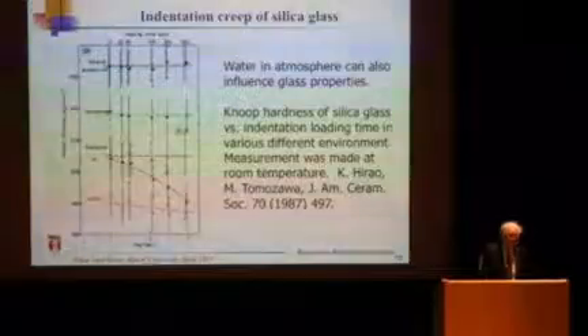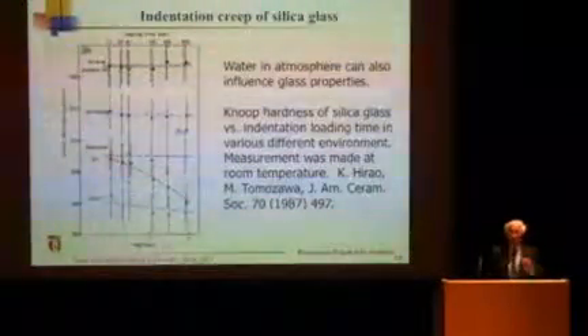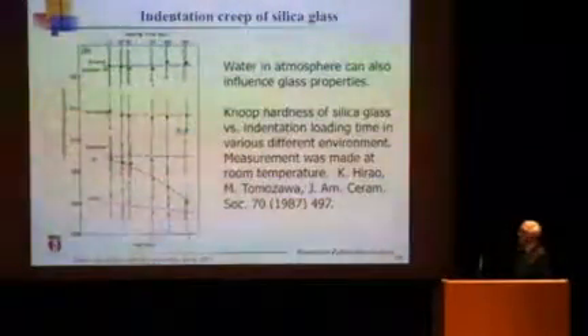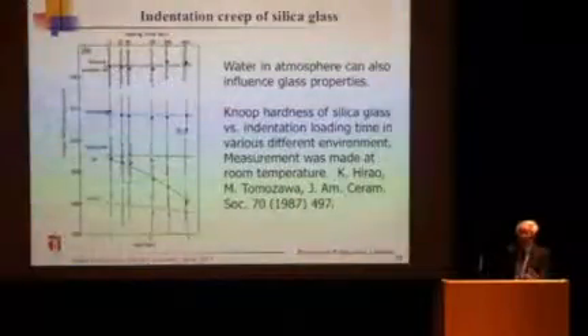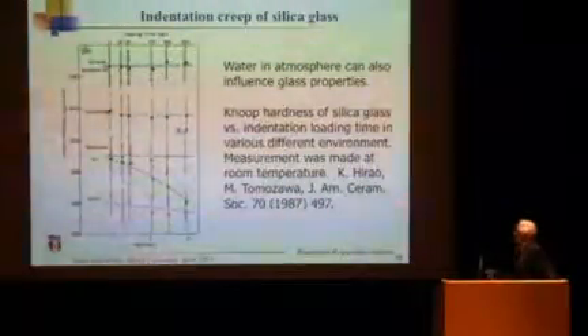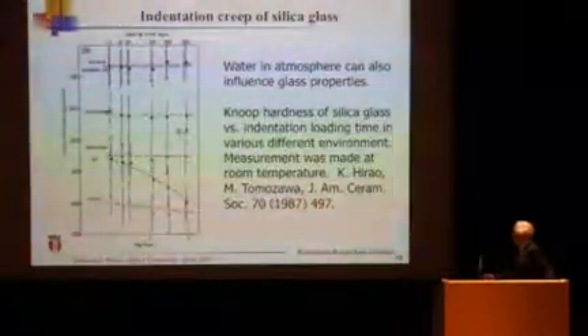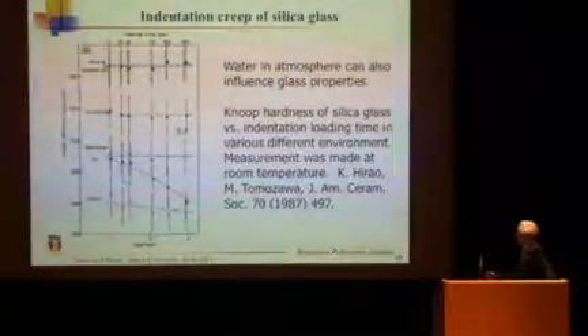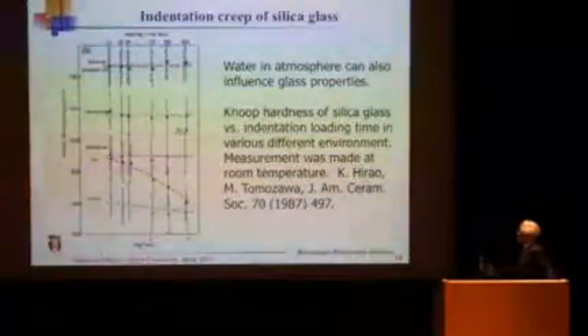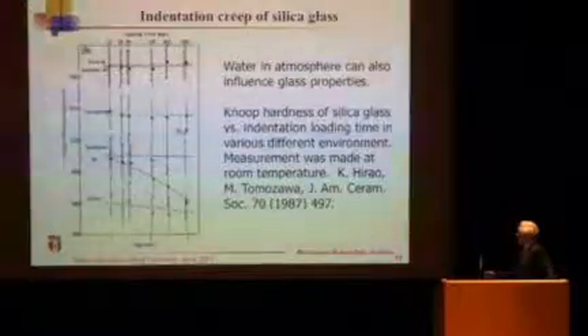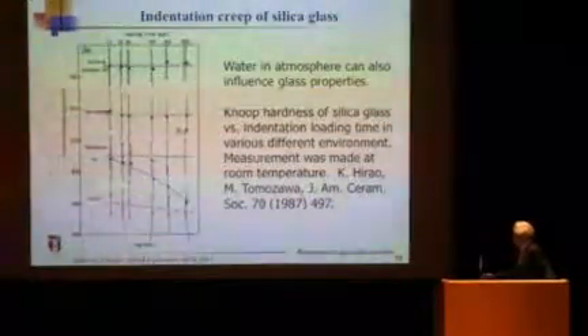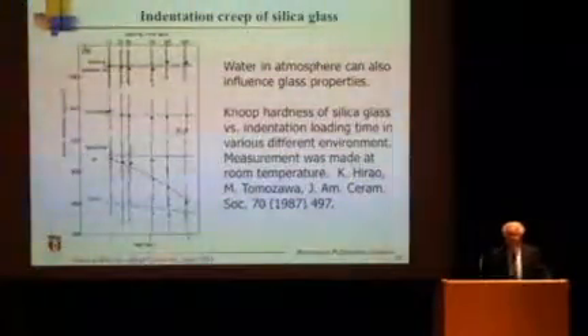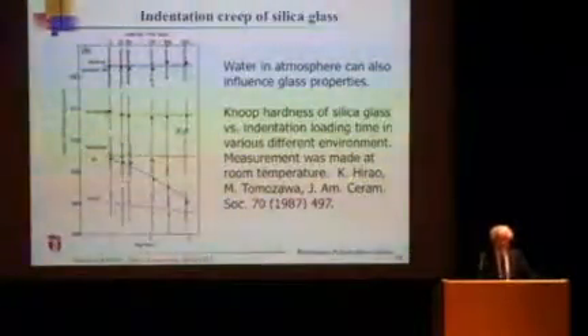Even if the glass doesn't contain water, if you measure some properties such as indentation hardness in air, then in air or water, hardness goes down. In other non-aqueous solutions, hardness does not change with time. So only when you have air or water does it go down, down, down with time. This phenomenon is called indentation creep.